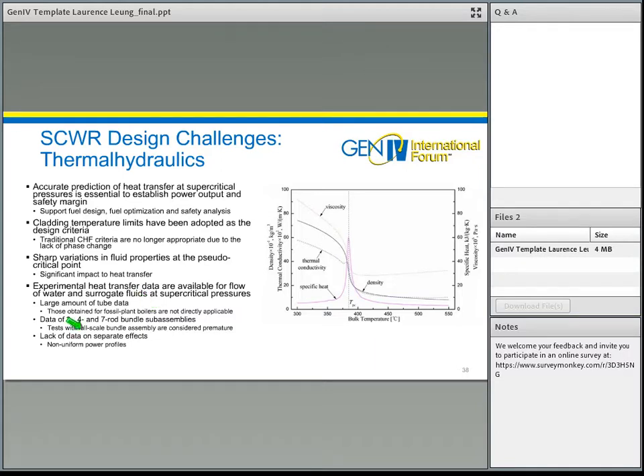And we also collected data for 3-, 4- and 7-rod bundle sub-assemblies. At this point, because we're still in a conceptual phase, testing a full-scale bundle is considered premature because we're still optimizing the fuel assembly, or improving the fuel assembly heat transfer characteristic. On top of that, most of the experiments are just operating or testing with uniform heating or reference cases. We don't have any data for separate effects, for example non-uniform power distribution axially or radially, and that is the information we need for the assessment of the heat transfer characteristic to establish the power generation and the safety criteria.